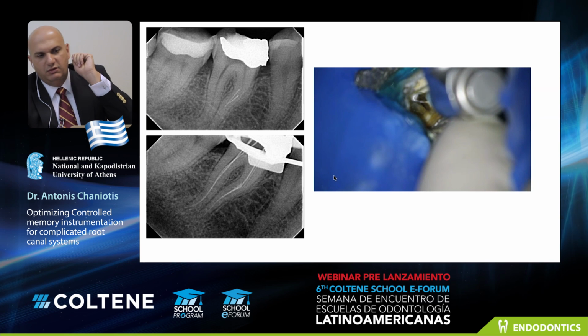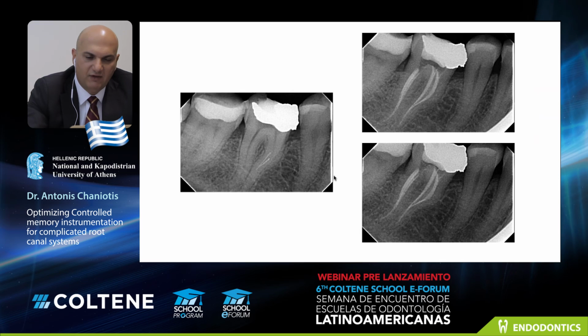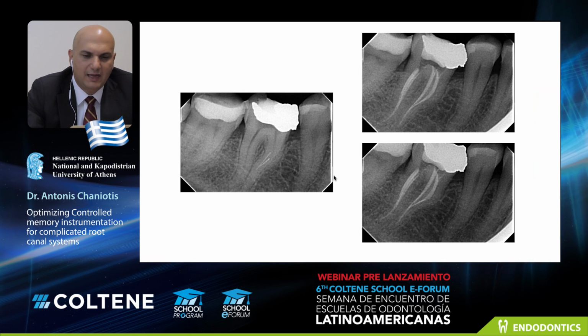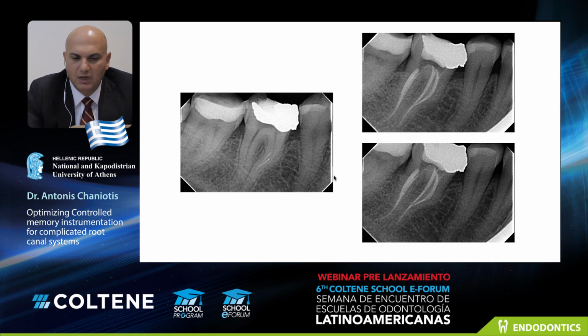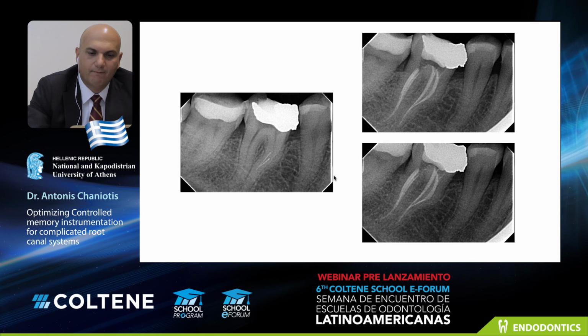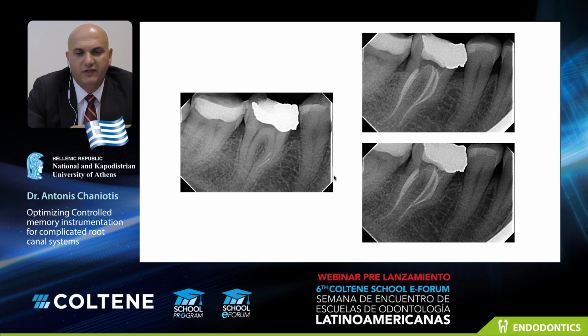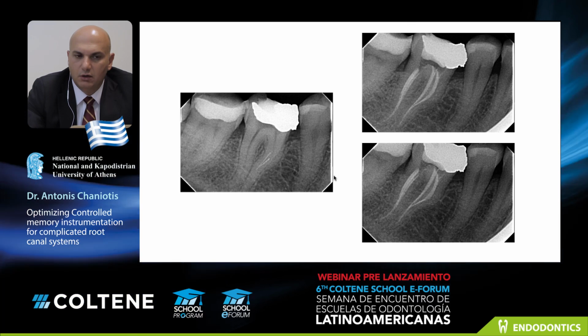In this case, this was the result with control memory files. Very difficult case. I didn't make any kind of attempt to remove the broken fragments. I just bypassed both of them, shaped with tactile control activation up to 30/.04, and this is the postoperative radiograph. Dilacerated canals, like this one, you can go up to 30/.04. You see, with this technique, you finish your preparation whenever you are able to drive your file to length without activation. And you can take also a radiograph, and you can see clearly in this sequence of radiographs how well it follows the anatomy.